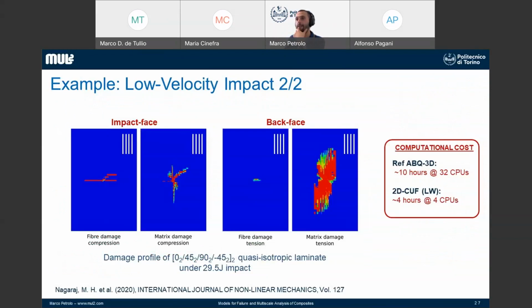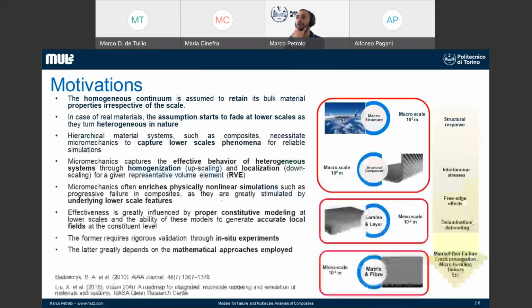And here you can see the impact related to the fiber. So this is the fiber damage under compression. Here we have the matrix under compression. So in a virtual platform for progressive damage, at the end of the day, you end up with this kind of results. And these are important to, for instance, modify the design of your composite plate or to track the progression of the damage inside your component. In order to get even more accurate results, sometimes you need to model different scales, as I said.